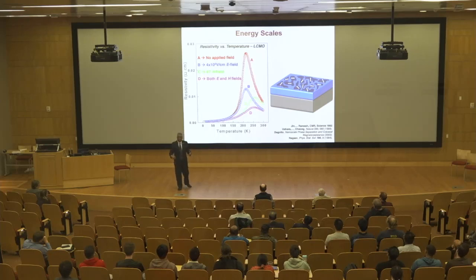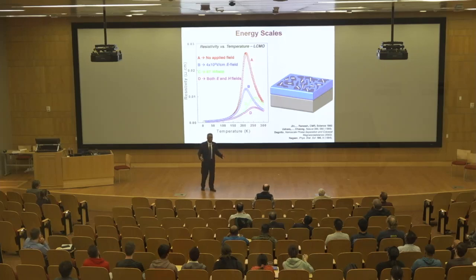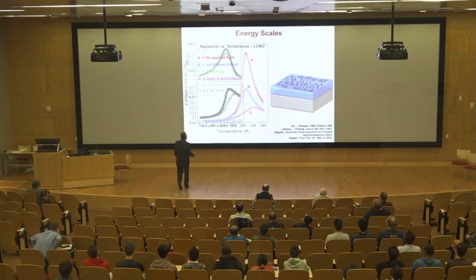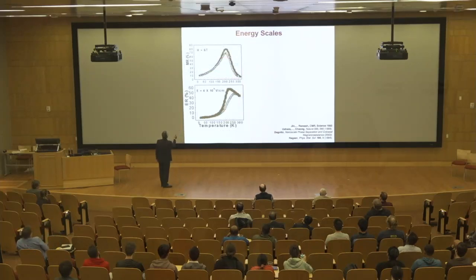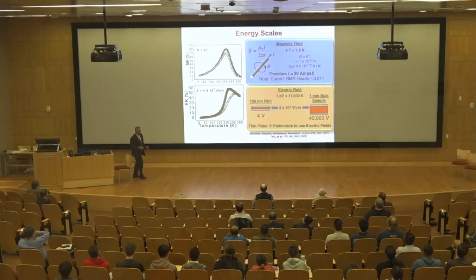Okay. And this material is a very fascinating material by itself. It has regions of ferromagnetism mixed in with regions of antiferromagnetism. Now, if you look at this, you can calculate the magnetoresistance and the so-called electroresistance. But here's the most interesting thing in this whole picture. If I look at the physics of the magnetic field, and this is just from a textbook, this is just Ampere's law. If I have a wire like this, I have a magnetic field given by the right-hand rule. To get a field of 6 Tesla at a distance of a micron, I need to run something like 30 amps. And first, blow up the wire. Second, blow up your bank because you need a big battery.